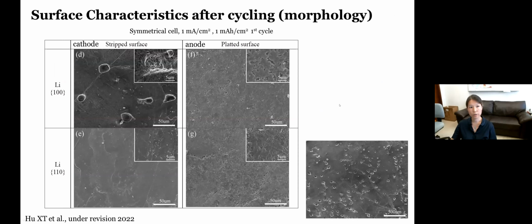We also look at the surface morphologies using SEM. And to our surprise, although this pitting was known a long time ago, we didn't expect to see such a huge difference on the lithium 100 and the lithium 110 surface. So this is the cathode side in the first cycle, so first half of the cycle, the cathode gets stripped. You see obvious pits are formed on the surface, but in the case of 110, you see none. They're very flat. And on the anode side, the difference is not very obvious.